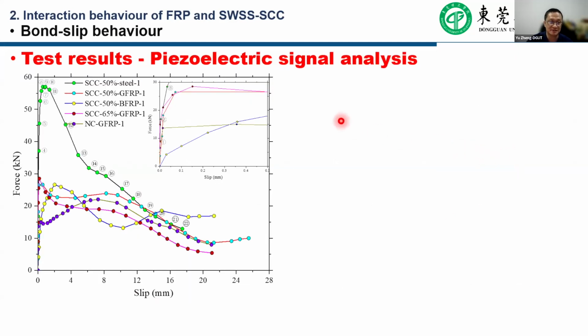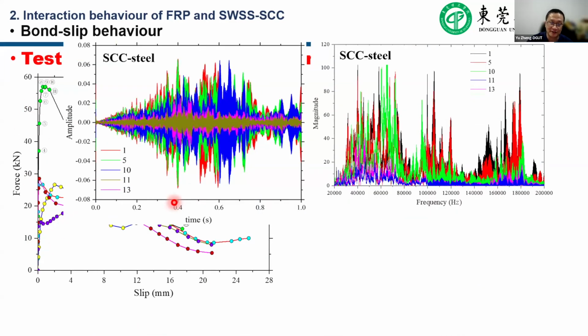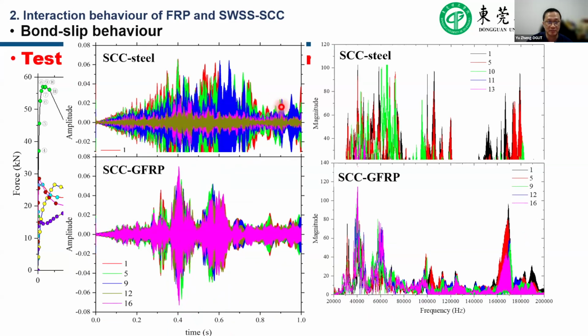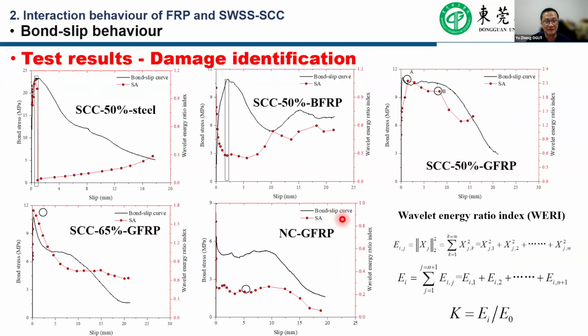In the second part of this stage, we use the piezoceramic to try to identify the failure modes of the bond slip, and try to quantify the damage level of the bond failure. That can be found at the beginning of the bond test, and this is with the pull-out test. The signal will change significantly. And after that, we use the wavelet energy ratio to establish the index to quantify the damage in the bond failure. And we can find that it shows a good correlation with the test result. Therefore, we can use that to quantify the damage level of the bond behavior of the FRP and the self-compacting concrete.